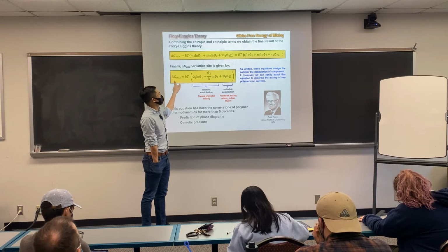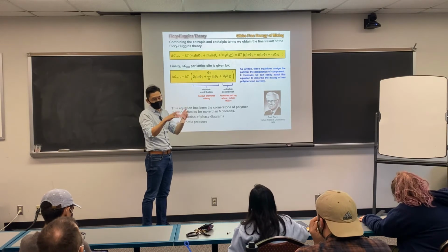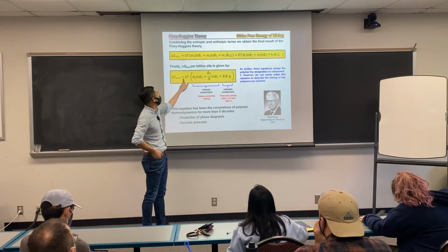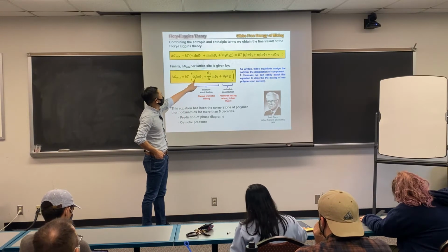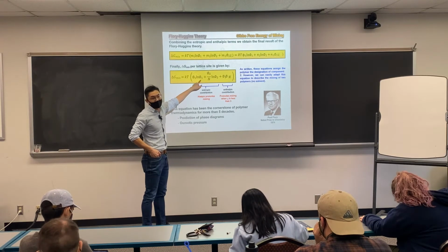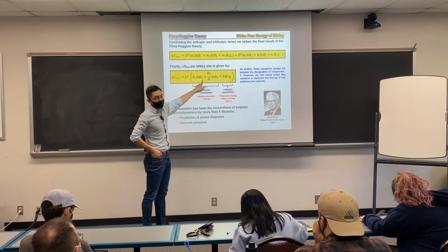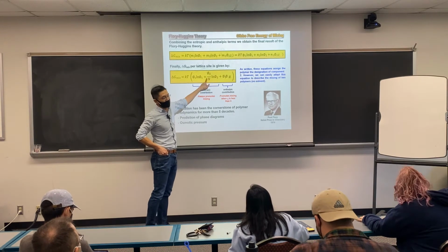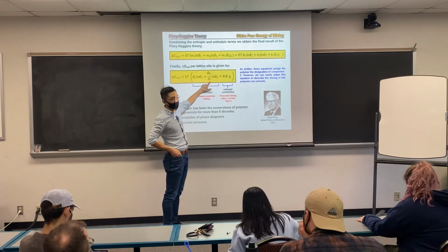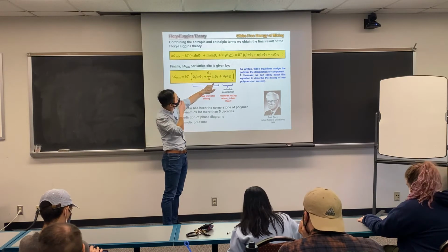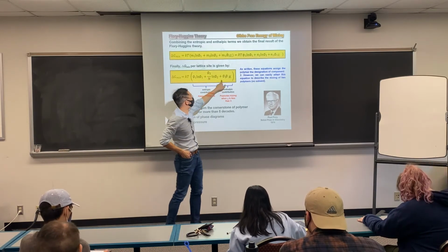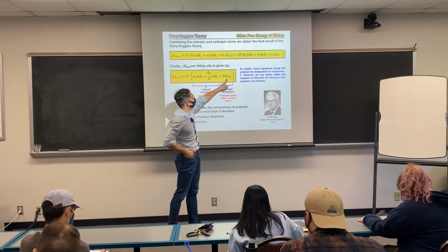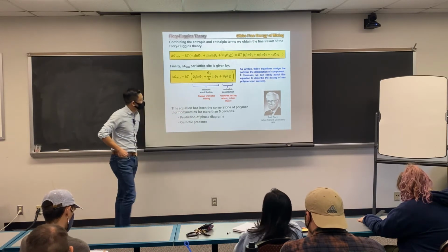This basically says that per lattice site, if you look at individual lattice sites, the average free energy delta G of mixing will equal kT multiplied by phi 1 log phi 1, the contribution from solvents in entropy, plus phi 2 divided by n, log phi 2. We talked about how the connectivity of the polymer lowers the entropy, and it's reflected here. Plus the interaction contribution, phi 1 phi 2 chi, okay?